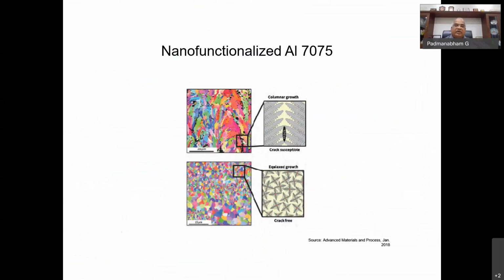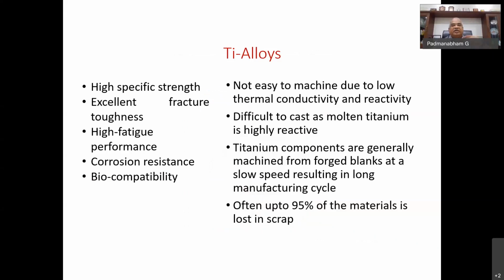And also there is an innovative possibility of avoiding the solidification problem by nano-functionalization, by adding elements like zirconium so that heterogeneous nucleation is promoted. And you can avoid the segregation pattern, as in the top picture, and end up with a very fine-grained structure, which helps in getting the good properties that you're looking for. Similarly, let's go on to the titanium alloys.